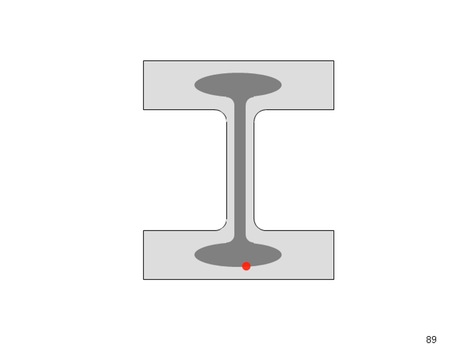Additionally, when the steel is rolled, the rolling action would break down these grains, causing them to become finer grains on the surface. The core region didn't require the same amount of rolling. And finally, these outside surfaces cooled more rapidly than this core region would. Now, for those reasons, and perhaps even others, there was a segregation that would take place. In shapes, we had reduced notch toughness in the steel.